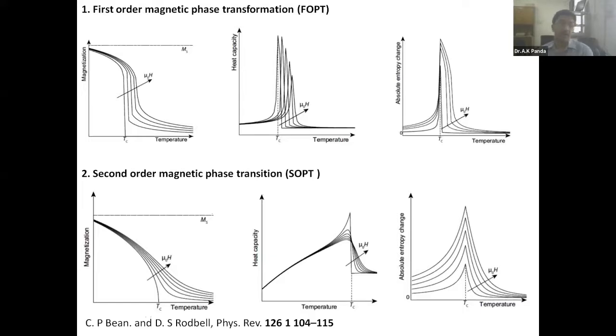Okay, and just to show how the magnetization would look if it is a first order or a second order transition: the top one, on the left side, is the magnetization plot, and you see that the transition is very sharp. As you go on increasing the applied field, you are able to shift it to the right, towards higher temperature. But in any case, they have a very sharp transition, because this is the interface where we are able to bring about magnetostructural transformations, right? So when you are able to bring out both events, the magnetic transition is quite rapid. And this is simply the heat capacity. You see all the transitions, whether the absolute entropy change, are much faster, and with the effect of the magnetic field, it shifts to the right.